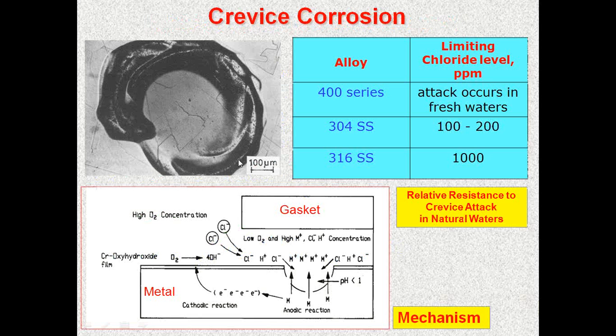Crevice corrosion is whenever there is a metal to metal joint, or metal to non-metal, the joint is undergoing selective corrosion attack. It happens due to the chloride level, and this is mainly because there is a selective depletion of oxygen here, and also the concentration of the chloride is different here. Chloride diffuses, and selective corrosion takes place between a metal and non-metal, like a gasket, or a metal and another metal. So where there is a restriction of space, say in micrometer square area, where diffusion of ionic species is not possible, concentration of the ions like chloride or depletion of oxygen leads to crevice corrosion.